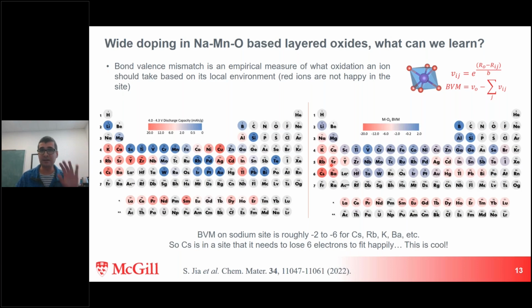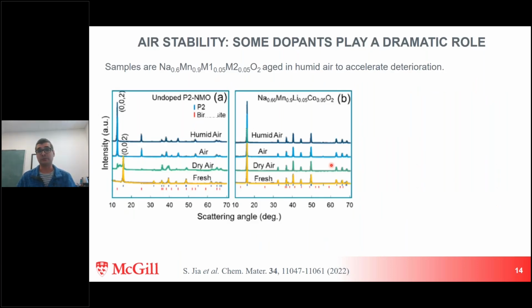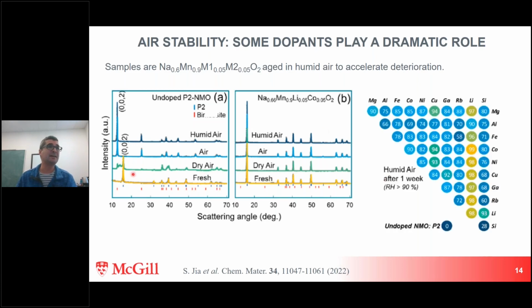Okay, so that little aside, but a really interesting story that came out of this. The other thing that was very interesting is that some of these dopants really dramatically improve the air stability. So I know my 30 minutes are basically up, so I'll just go through this quickly. If you look at an undoped material in a few weeks in a humid atmosphere, it completely converts from its pristine phase that you can see with this peak in the XRD to something else.